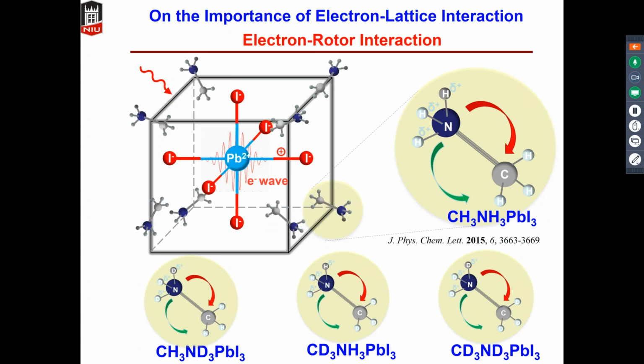In order to have a fair comparison, we made single crystals of the 4 different types of isotoped MAPbI3. And we carefully examined their crystallinity. We first cleaved the single crystal and checked the cleaved surface, and we found it is very smooth. There are no cracks on it, so it makes us very comfortable.